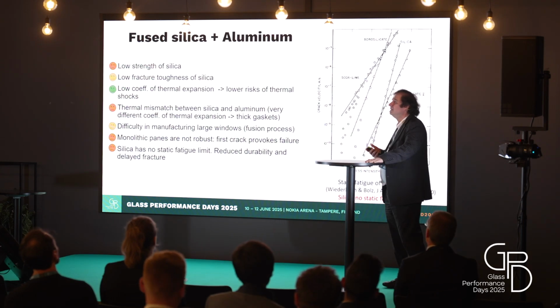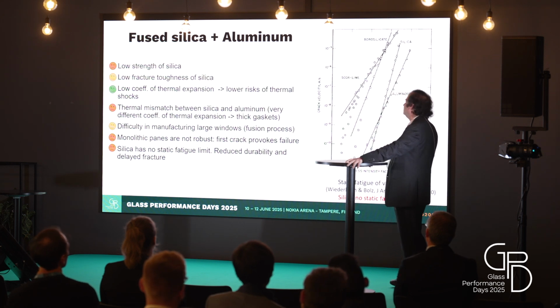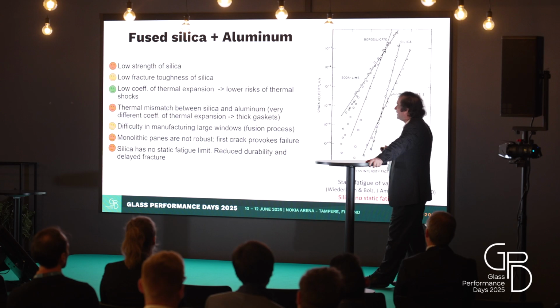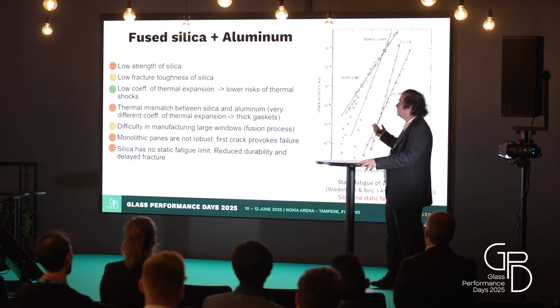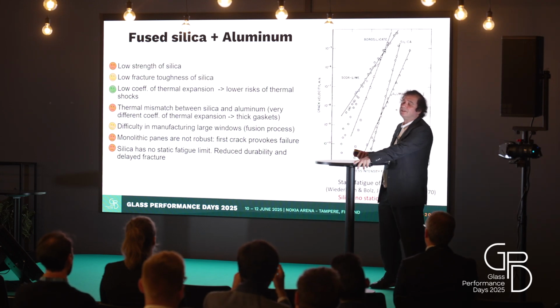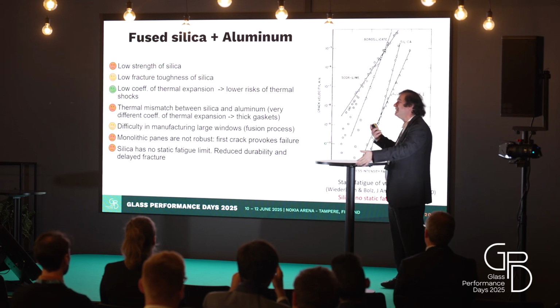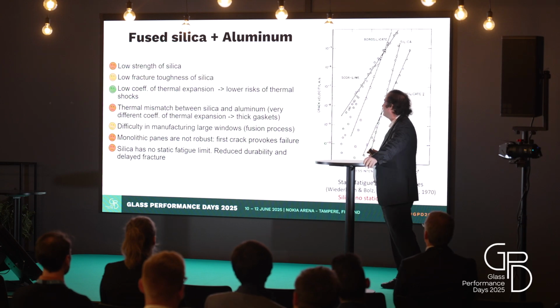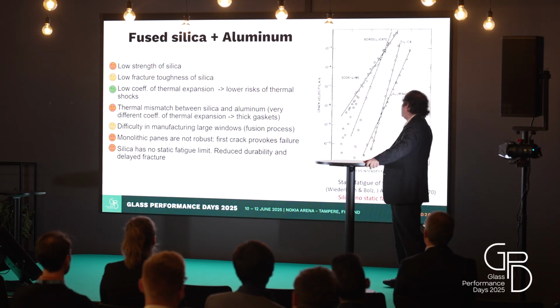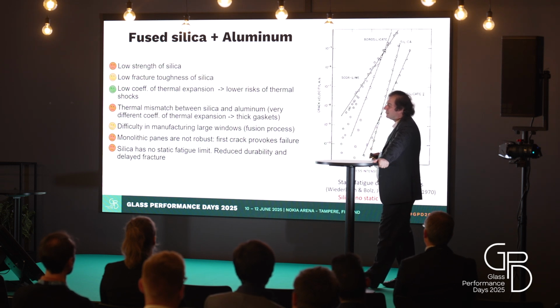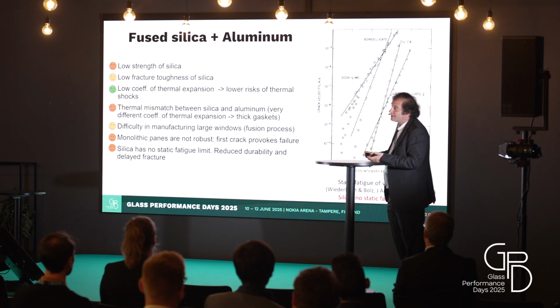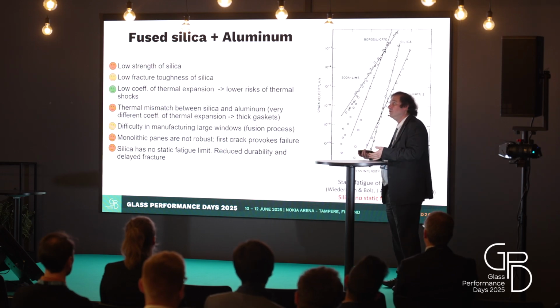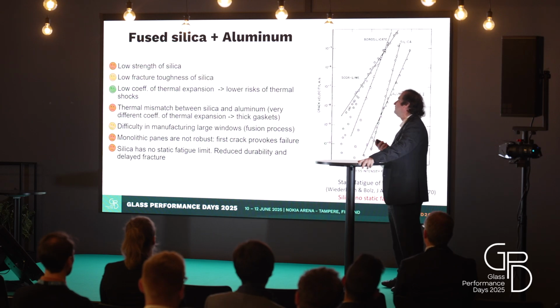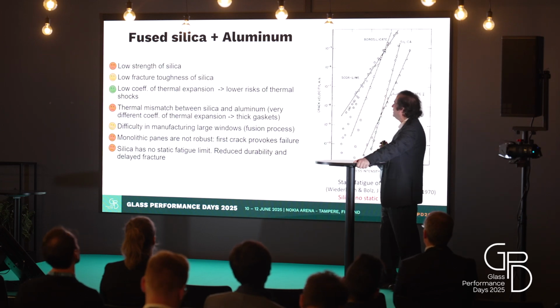There are, however, some drawbacks for fused silica and aluminum frame. First of all, the bending strength is not so high. The fracture toughness of fused silica is not so high. It is true that there is a very low coefficient of thermal expansion, so that an uneven temperature distribution does not cause any big thermal stress inside the material, but there is a thermal mismatch between the aluminum frame and the fused silica. This stresses the gaskets. You know that everything should be airtight, and consequently the gaskets are very important elements in the window design.